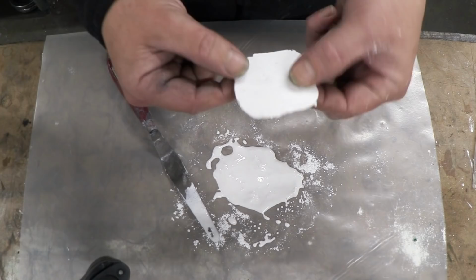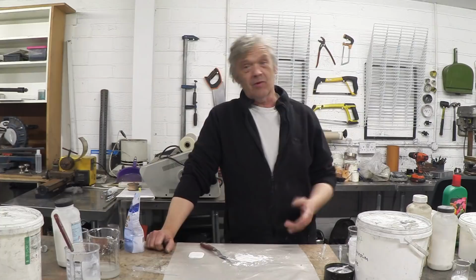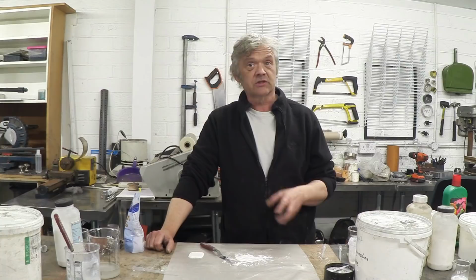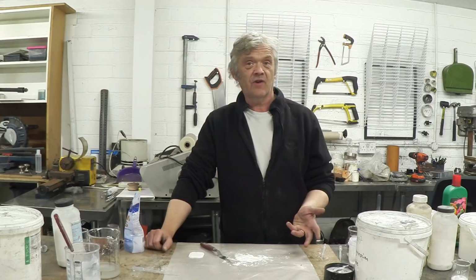So these cements that we're going through, rather quickly as it happens, all have one key problem with them, and that is they're a bit sensitive to water. So if you leave them in a wet condition for a long period of time, those soluble salts will leach out and it will reduce the effectiveness of the cement. But they are really, really good in lots of other circumstances. Like I said, the very basic Sorel cement was used for billiard balls, fake ivory, it can be turned in a lathe, it's awesome stuff, but you've got to keep it dry.